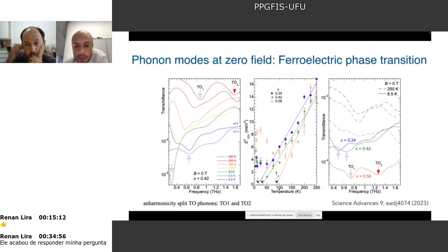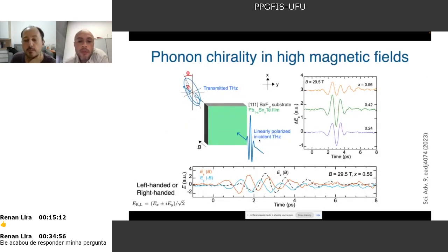Okay, so let's keep the temperature very low, like 10 Kelvin, so that all the samples will be in the ferroelectric phase, and then apply a magnetic field. So here I have the sample. I put this perpendicular magnetic field, lead tin telluride, different concentrations of tin, linearly polarized terahertz pulses, and then I will characterize the transmitted terahertz pulses, two components: change of polarization, which is called Faraday rotation, and change in ellipticity from linear to elliptical.